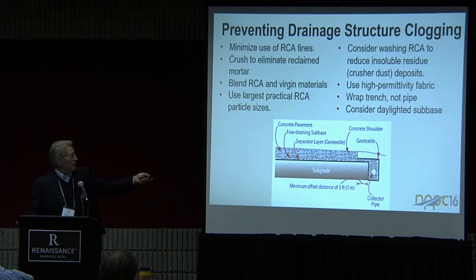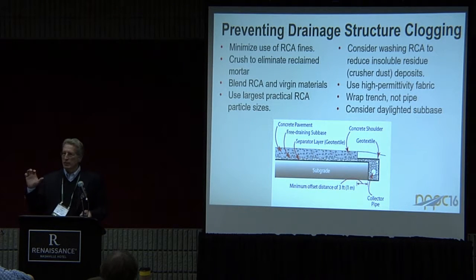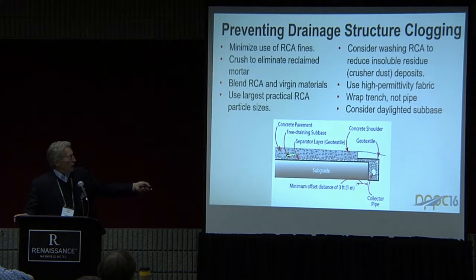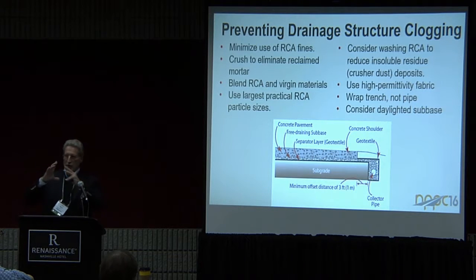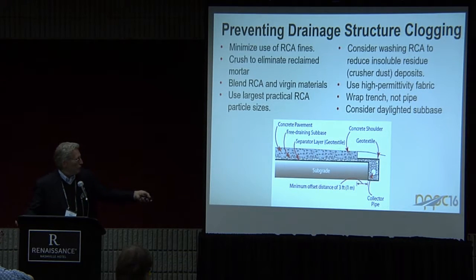Use fabrics that have a very, very high permittivity, so that if they do get a little bit of clogging on there until the situation stabilizes, they're still going to carry water. Wrap the trench instead of the pipe. What we saw early on, 20, 30 years ago, was people using fabric wrapped pipes. You remember that? And of course, that concentrates all the dust and stuff in a very small area. If we wrap the trench rather than the pipe and allow the water to flow into the pipe, we eliminate the clogging at the source. And then finally, probably the easiest thing, what ACPA recommends, is just to daylight that subbase.